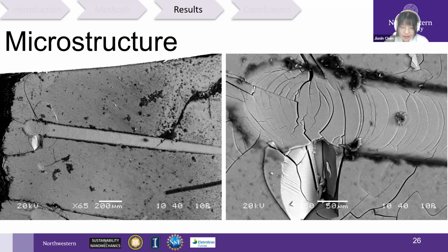After scratch testing, the top surface of the specimens was examined using scanning electron microscope at different levels of resolution. Let us take a closer look at the fracture surfaces. The first figure represents the scratch panorama. We can see that the scratch starts from the right-hand side and then stops at the left-hand side. The second figure is a closer look at the final location of the scratch testing.